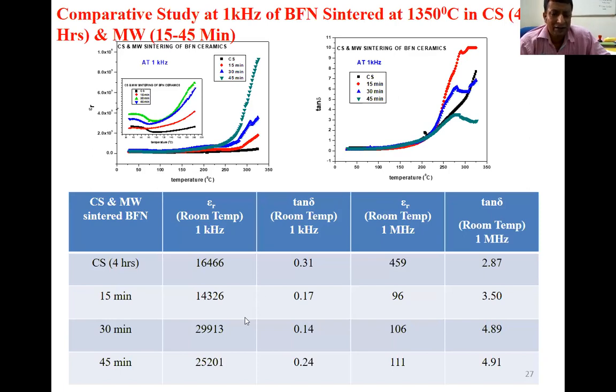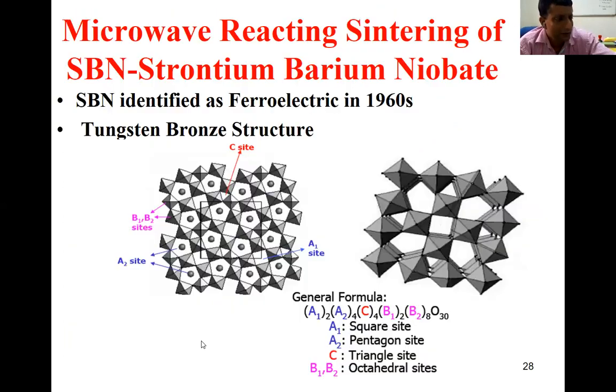Now let us appreciate the dielectric properties, because this BFN is a high dielectric constant material. You see here the dielectric constant at room temperature is near about 16,500 at 1 kilohertz frequency. In the case of the microwave sintered samples, we obtain near about 30,000, nearly doubled, and the loss also reduced very much. In this dielectric constant system, the dielectric loss is a big issue. So we exploited the dielectric loss factor, and we obtained better dielectric properties in the case of this BFN system. So this was the case of the BFN. As I told, I have to be a little fast actually.